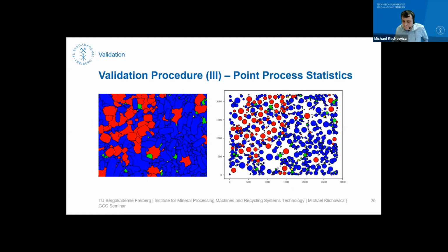And there's another even more standardized approach in statistics, and that is point process statistics. And I applied this point process statistics to validate whether the microstructures are comparable or realistic or not. And the idea is pretty simple. If we have such a microstructure, we replace each grain by a point. For example, if we have this red grain here, we take a bounding box of the grain, and replace this grain by the middle point of the bounding box. And additionally, we can add size information to this point, for example, by using a bigger red mark for a big grain, or a smaller red mark for a smaller grain.